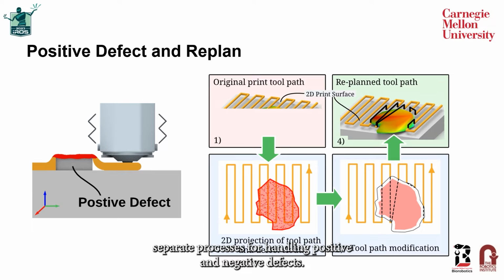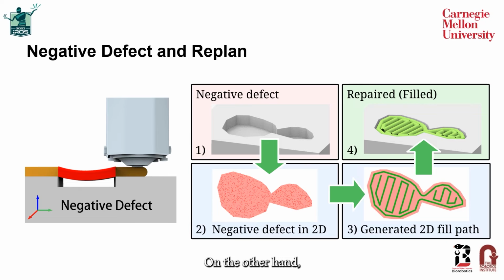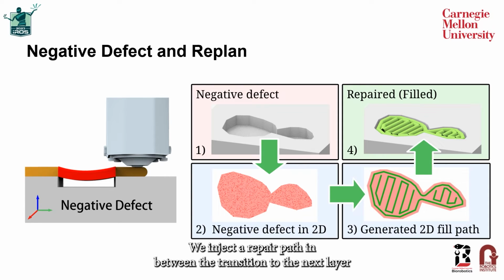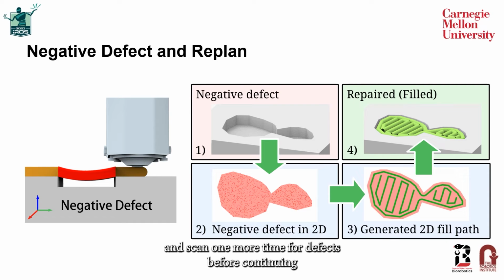We have separate processes for handling positive and negative defects. Positive defects, characterized by excess material, are remedied by replanning the extrusion trajectories of future layers to avoid adding more material to the defect. On the other hand, negative defects have a lack of material which we need to fill in. After performing the scan and identifying the defect, we inject a repair path in between the transition to the next layer and scan one more time for defects before continuing to the next layer.